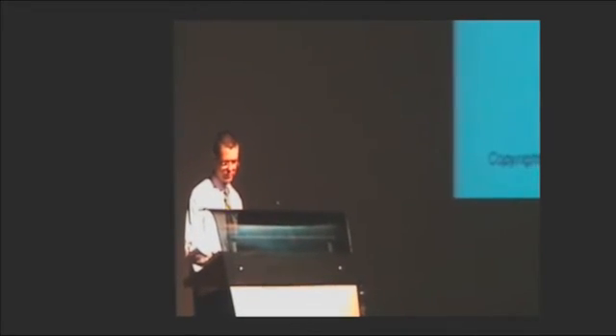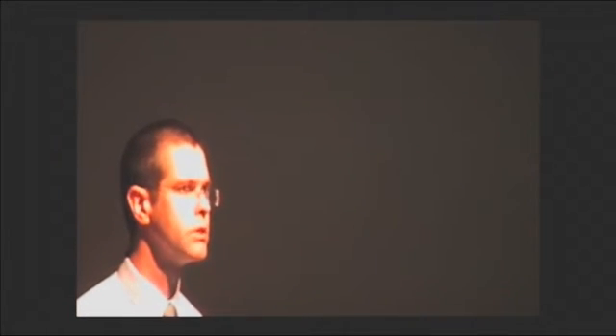What was the cobalt loading in the support in catalyst? Sorry, I missed that. What was the cobalt content in the catalyst? Okay, cobalt content for these model systems that we've used ranged quite a lot. You'll see one, for instance, the last one that we aimed for. I can just perhaps quickly go there if the chairperson would allow me to do that. There you have, for instance, the fourth sample. You could actually get 1.5 grams of cobalt nitrate into this support, but you can work it out. You aim normally for complete full filling, and if you know the density of the cobalt nitrate, you can work out how much cobalt you can load. So anything from 20 grams per 100 grams support, even up to 50 grams per 100 grams support that you can load, depending on the number of impregnation steps as well.